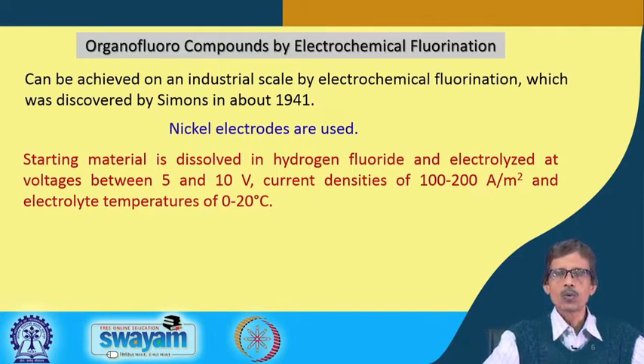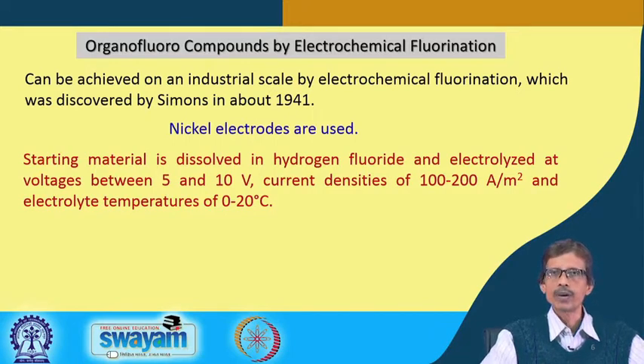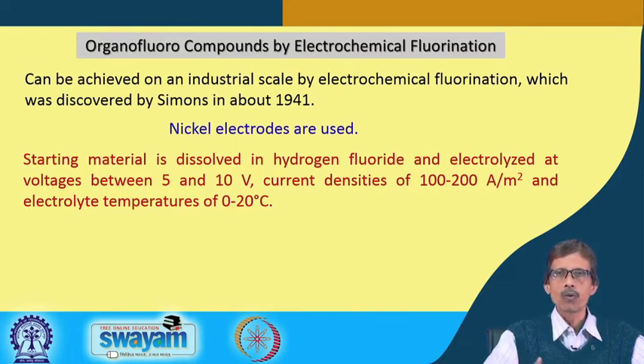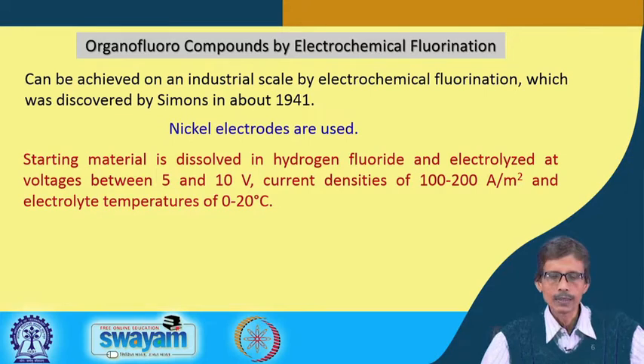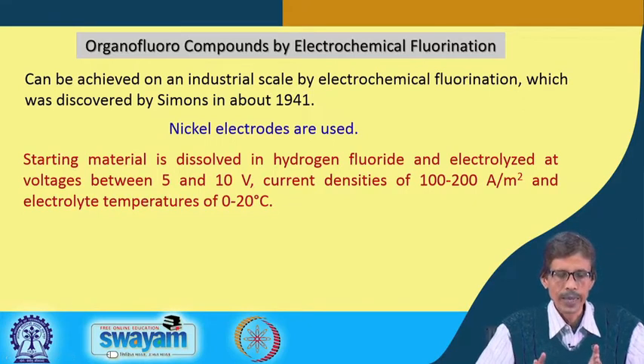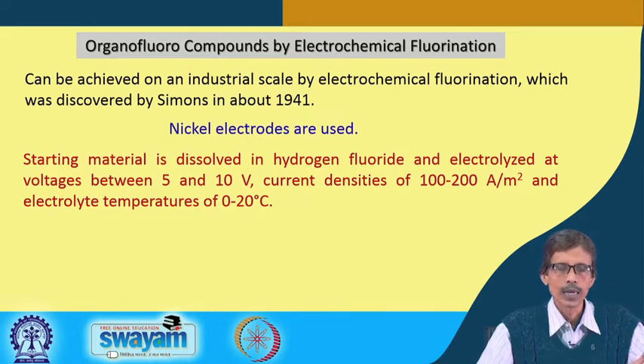The organic molecule where we substitute C-H functions with C-F functions is dissolved in hydrofluoric acid medium, because in that medium you can perform electrolysis. The hydrogen fluoride medium is electrolyzed at a voltage window of only 5 to 10 volts, so a battery-operated setup is also possible.